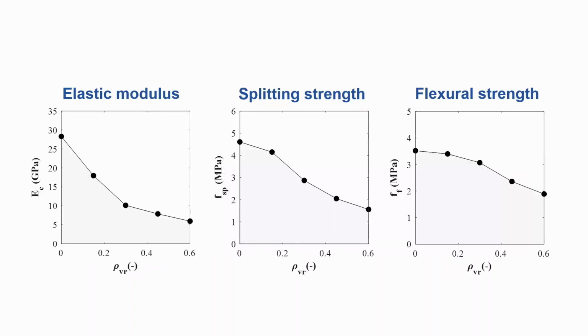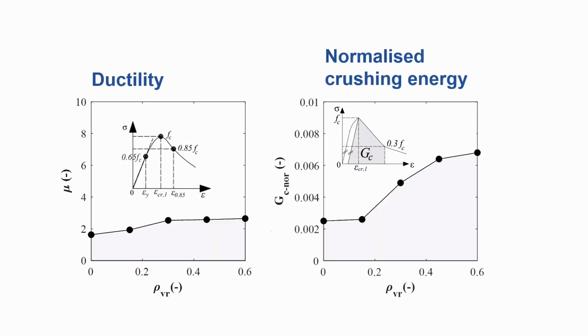Then these are other mechanical properties, including the elastic modulus, splitting tensile strength, and the flexural strength. Plotted against the rubber content, and they follow the same trend we see for the compressive strength, and that's the more rubber you have, the lower the mechanical properties we see.